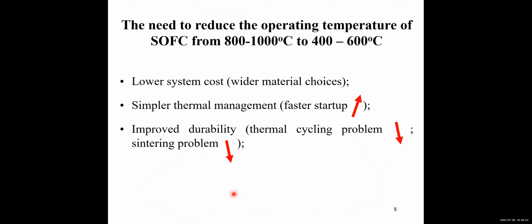In order to reduce the cost of the SOFC system and improve the durability, it's very important for us to reduce the operating temperature from very high, about 800 to 1000 degrees Celsius, down to about 400 to 600 degrees Celsius. Because at a lower temperature, we have a wider material choice, so it's possible for us to use cheaper materials.